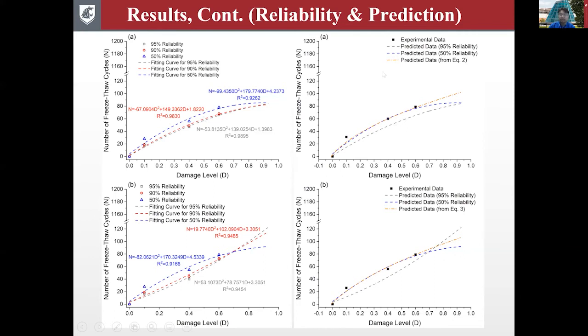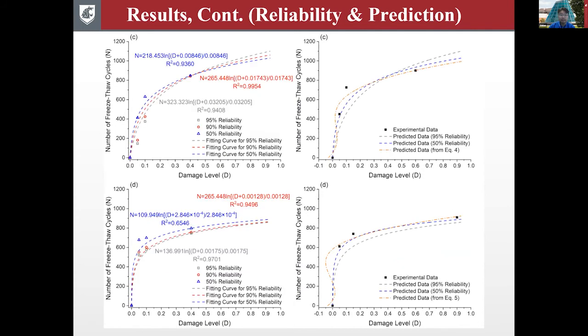And also, we compared the prediction based on Weibull distribution model with the curve developed based on the polynomial equation that we developed previously, and also with the experimental data. As can be seen, the Weibull distribution model with 50% reliability can provide a more accurate prediction and more close to the experimental data. Here's the prediction for the control specimens, and here's the prediction for the self-healing concrete specimens.